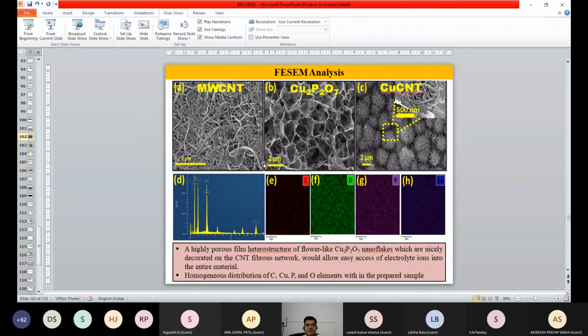So here you can see that this is a carbon nanotube, right? And this is copper phosphate, Cu2P2O7, on the stainless steel. But whenever we deposit this copper phosphate on carbon nanotube, we observed a microflower-like morphology. It gets converted to the microflower-like morphology. So here you can see the microflowers of the copper phosphate on the carbon nanotube, right? And that is the beauty of this: whenever you deposit simply copper phosphate on stainless steel, it shows fibrous-like morphology. But when you deposit copper phosphate on the carbon nanotube, you not only get the fibrous morphology, but also the microflower-like morphology, right?